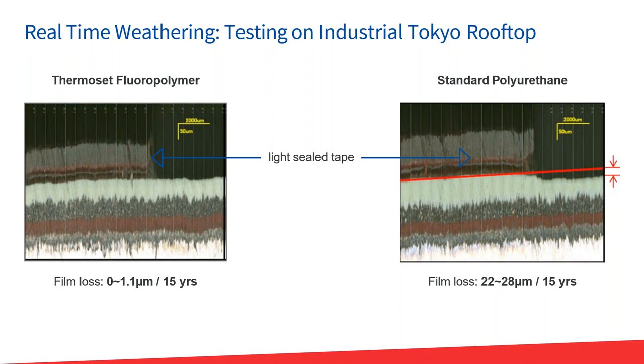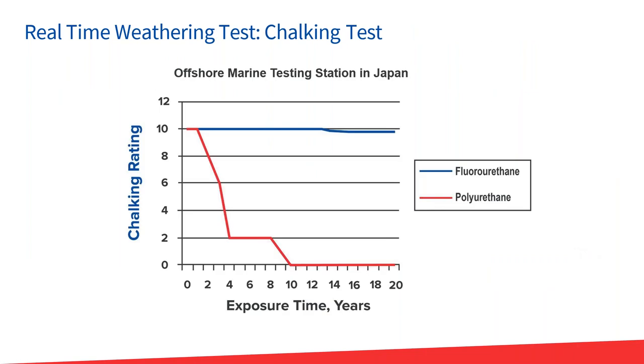I would argue that's really not too bad for a conventional system, but if you look on the image on the left of the thermoset cross-linked FEVE system, you see that adjacent to that light sealed tape where it was exposed, you really can't measure the erosion. And if you do, you may get a micron or two in certain areas. So that's really key to how these materials can protect against corrosion, because they're maintaining the film, and the integrity of the film is there. So it can act as a barrier for a very, very long time.